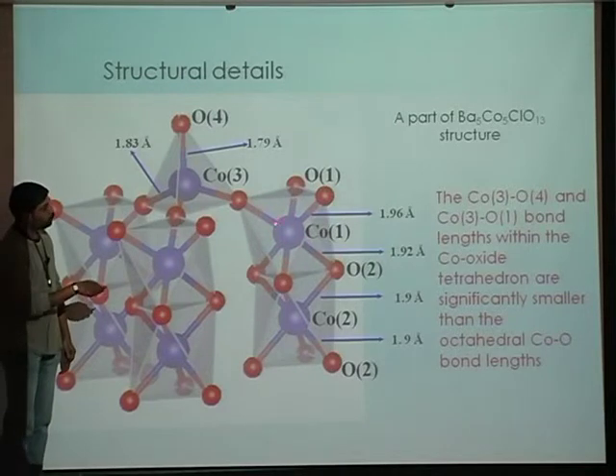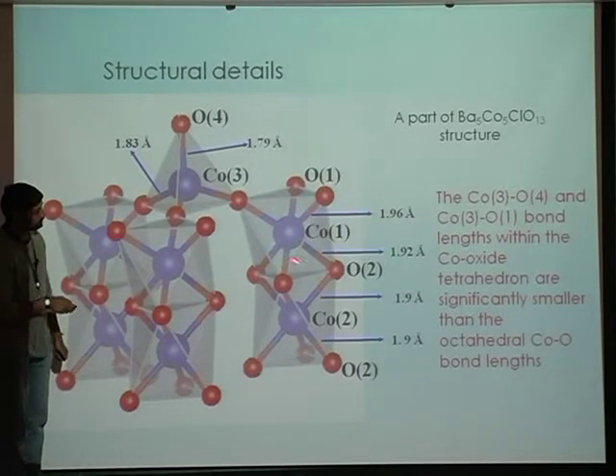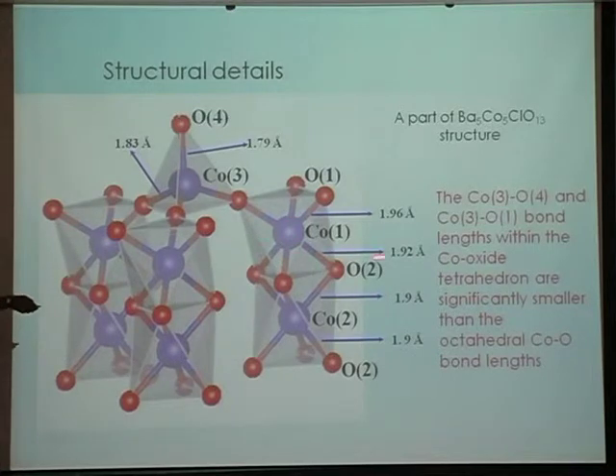Look at this cobalt 1-O1 bond, that's 1.96 angstrom. This is cobalt 1-O2 bond, that's 1.92 angstrom, and these two are 1.9 angstrom. So all the bond lengths are in the range of 1.9 to 1.96. Now if you go there, the bond lengths have reduced drastically. Cobalt 3-O1, so this is also O1, this is also O1. Cobalt 3-O1 bond length is 1.83 angstrom, and this is O4, that's 1.79 angstrom. So suddenly, in case of tetrahedron, you find that all oxygens are coming closer, making shorter bonds.